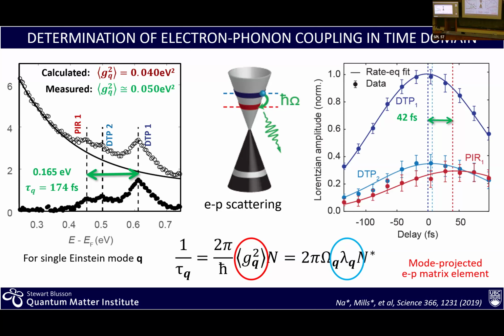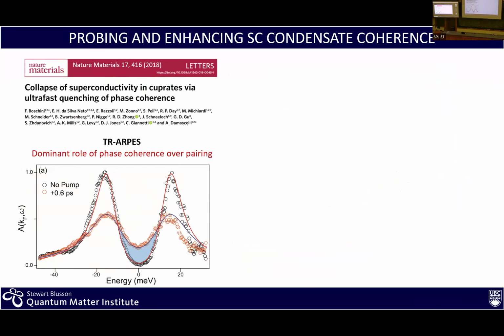And so by following this, by modeling this data with rate equations, we can extract the electron-phonon scattering time, 170 femtosecond, and from that, we can extract g, which we measure as 0.05 electron volt squared, and we can also calculate 0.04, and you see how in good agreement these are for a simple system like graphite. So that's one way to show how new techniques really can give you direct access to some of the fundamental quantities. And last, just two examples.